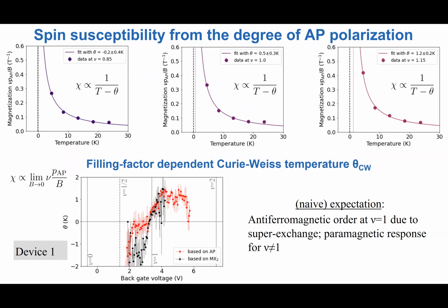And what we see is that the Curie-Weiss temperature is positive on the doublon side, when we have more than one electron per site. It's negative on the hole-doped side, and it's about zero at nu equals one, where you would normally expect interesting magnetic properties. It's a triangular lattice, so you would expect superexchange to dominate, and then you expect antiferromagnetic order, which should show up as some negative Curie-Weiss temperature. Well, we see that it's essentially zero.